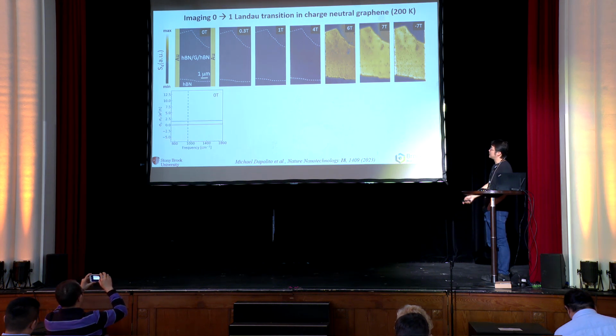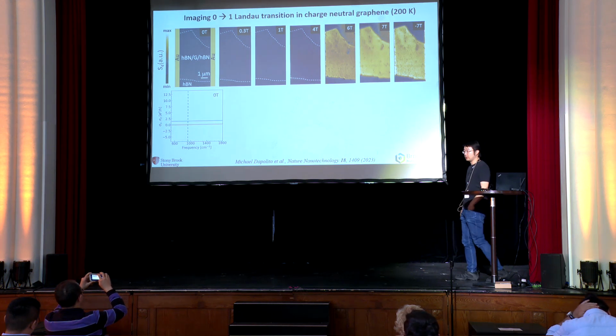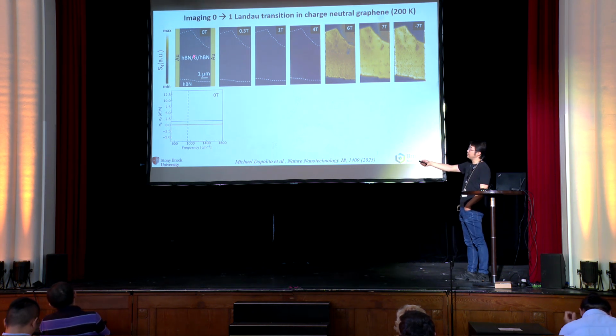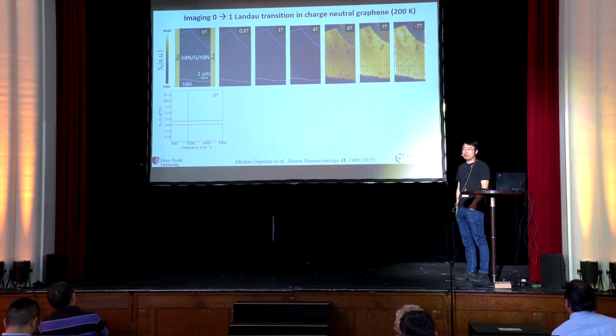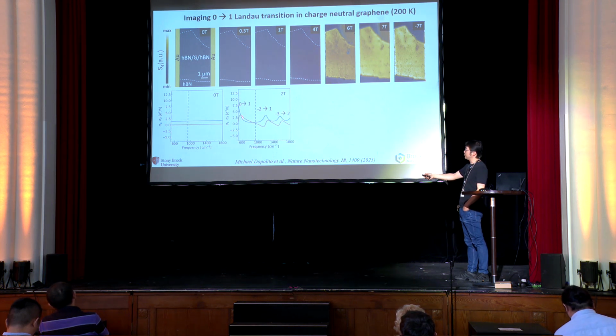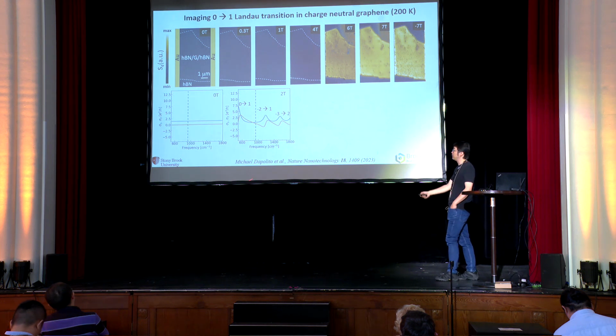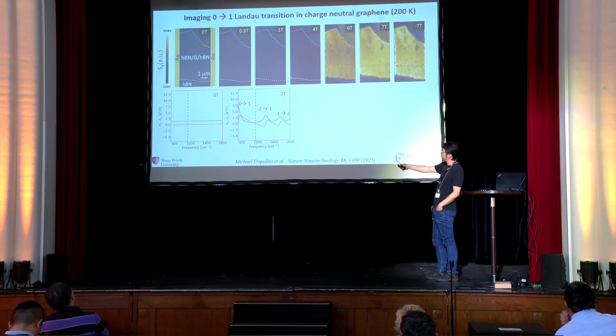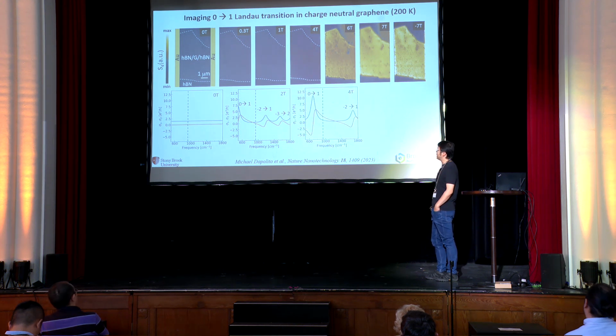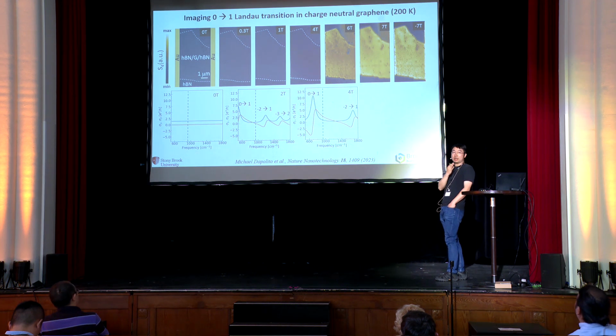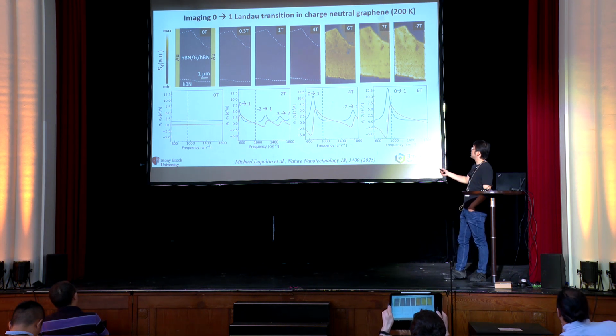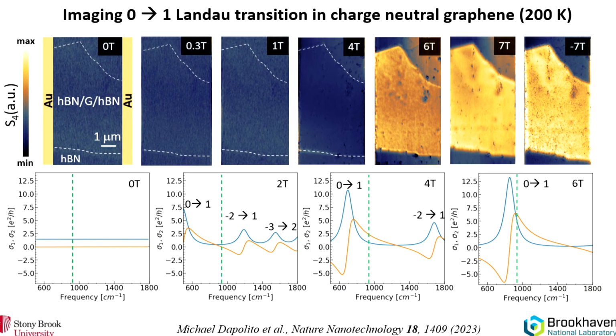This is simply because at low magnetic field, you have this universal optical conductivity, which is very low, so you do not see much at low magnetic field, right? This is basically an insulator, since this is charge-neutral graphene. And as you apply magnetic field, you form these quantized Landau levels. At low magnetic field, your laser frequency is not on resonance with these peaks, for example, the 0 to 1 peak. But as you increase your magnetic field, these peaks shift to higher frequencies. And now at 6 Tesla, your peak arrives at the laser frequency, so that you can see this on-resonance interband Landau level excitation in real space.